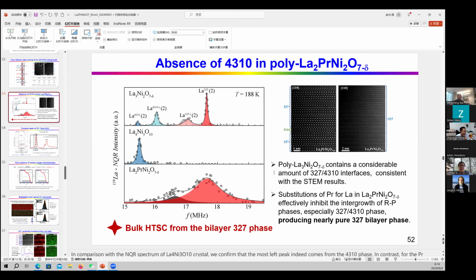Right. But the doped sample has a fully occupied O1 site. Yes. Which is different from the original theoretical hypothesis that you need to remove it for high Tc, right? But here you're saying you don't need to remove it. No, I think according to some theoretical proposals, O1 should be important, because for the dz2 orbital in the bilayer, you need the O1 oxygen to bridge this interaction. I don't know, maybe these two factors are correlated. Because we have no intergrowth, we therefore have no oxygen vacancy at the O1 site. So I have a strong belief they are correlated with each other.